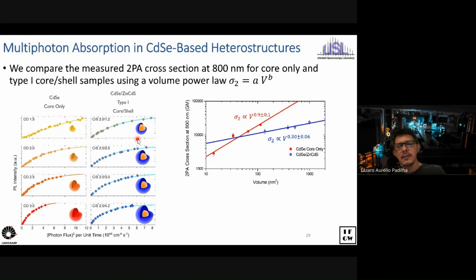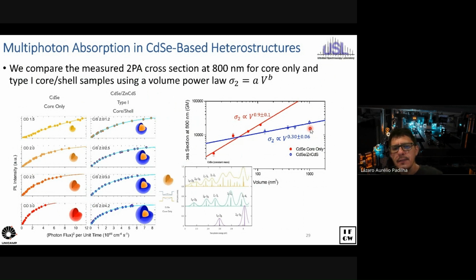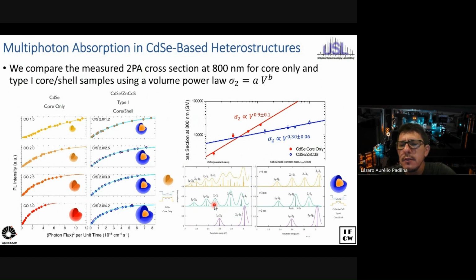So to understand what's the effect of core shell on the two-photon absorption. And when we did that, we see, of course, for core only, this linear dependence with the volume. Exactly how people have seen for the last 15, almost 20 years. Conversely, for type 1 core shell, we see a sublinear volume dependence. You increase the total volume, you barely change your two-photon absorption cross-section. And the way we understand that is that when you change the size of the core only, you really change a lot your density of states. However, that's not so true for type 1 core shell. So as you just change the size of the shell, you change much less your density of states.